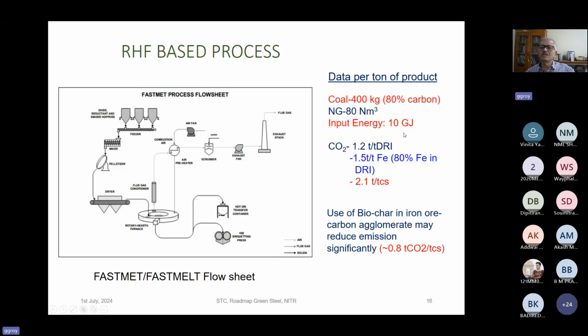Total input energy is around 10 gigajoule, and the CO2 emission is 1.2 ton per ton of DRI because the carbon input is significantly lower. It can be 1.5 ton per ton of iron produced, considering 80% iron in the DRI, and it will be around 2.1 ton of CO2 per ton of crude steel, considering the melting energy and associated CO2 emission. So here, as I said, there is a scope of biochar in the composite briquette or the pellet, because it will completely replace the fossil carbon by a carbon neutral biochar. In that case, even if you use natural gas for heat production, your CO2 emission can be significantly reduced to 0.8 ton of CO2 per ton of crude steel.